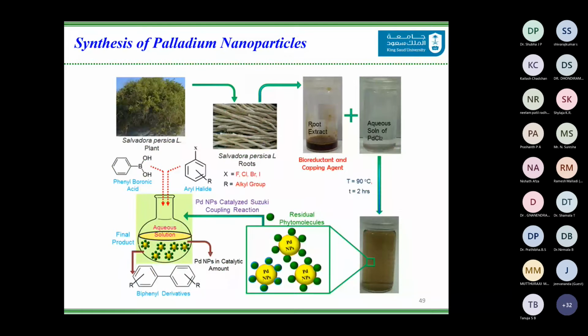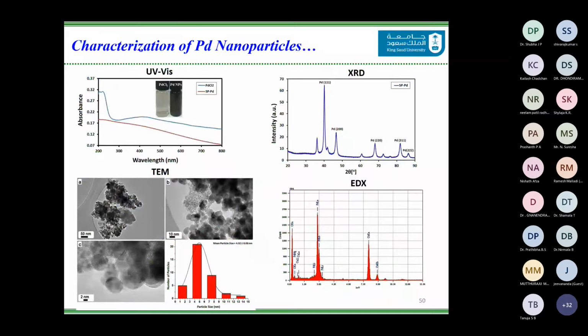Moving ahead, we used Salvadora persica for the synthesis of, again, the palladium nanoparticles to see how it works with palladium. And we were very happy that we got amazing results, confirmed by UV-vis, and the crystalline nature was confirmed by XRD. And you will see in the XRD spectrum additional diffraction patterns along with the palladium diffraction pattern, and this is because of the inorganic moieties present in the plant extract, which reveal themselves in the XRD spectrum.